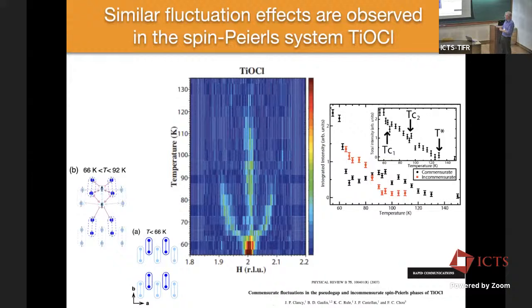But if you just imagine taking this and adding everything up, you get this very straight line behavior over a very extended range. So we have seen this before in two-dimensional systems, where if you add up all the fluctuations and the long-range order, you get something that looks very linear. So it's unusual, but it's not unheard of.